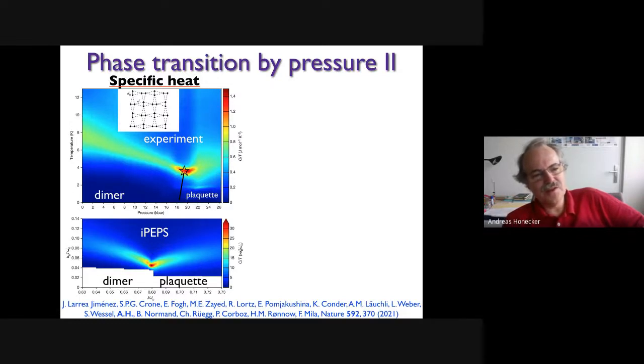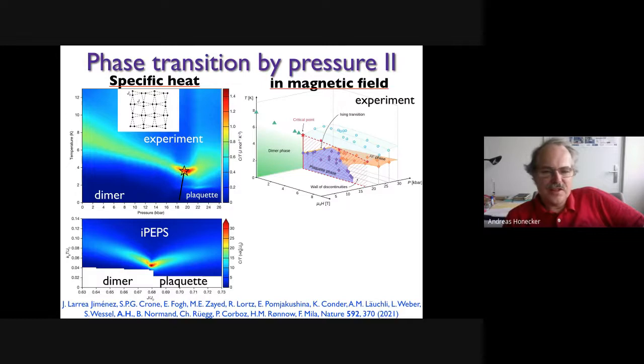This is iPEPS, and you can see exactly the same features. And you can actually also then use that to draw the phase diagram in the external field. And you have this dimer phase that is stable in an external field. The plaquette phase also survives a bit of an external field. And then between them, there's a surface of first order transitions. And this surface of first order transition then actually terminates at this temperature of roughly 4 Kelvin at a critical point. Good.